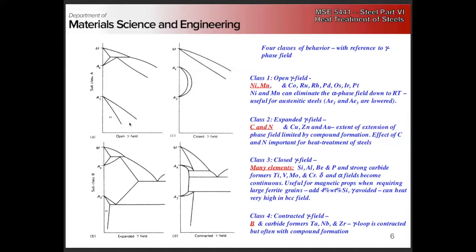So where is austenite on this phase diagram? Right, so it's this region here, right? So up here is the peritectic point. Here we normally have a eutectoid, right? It's absent, right? And so if we're at kind of a high enough concentration, we can go completely austenitic down to room temperature, right? We can eliminate the crossing into the ferrite region, okay?